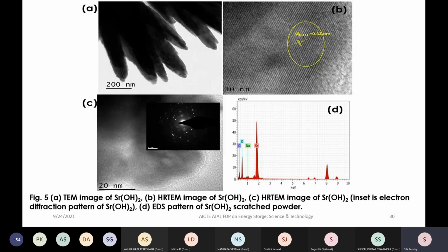then two cycles, then three cycles, and so on. If you are completing a large number of cycles, then only a very small amount of the strontium hydroxide is going to attach on the substrate. Then we have to take it out and do it again and again, so that the required amount, which is very small, is deposited, but it has taken a long time to deposit manually. So the students have really worked hard here. As I was saying about the carbon, one can see that carbon is present here, and this is the strontium, a strong peak is there, oxygen is there, and other things are also related.